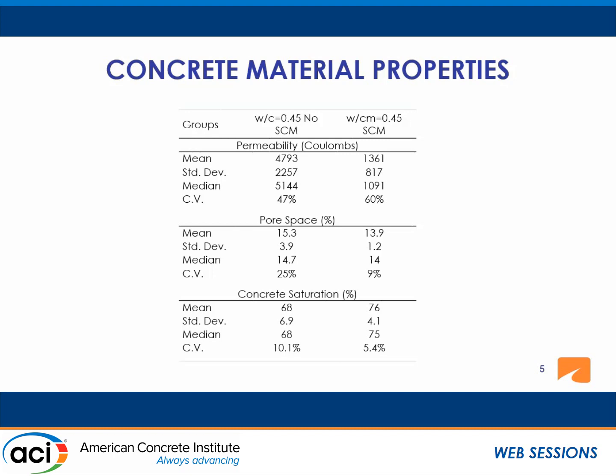But the concrete moisture saturation was opposite. We had significantly higher concrete moisture saturation in the supplementary cementitious concrete. The reason might be that there are fewer pores to fill, and the pores are probably smaller, so once the moisture gets inside, it's hard to get it out. And there could be differences in the distribution and the continuity of the pore system as well.